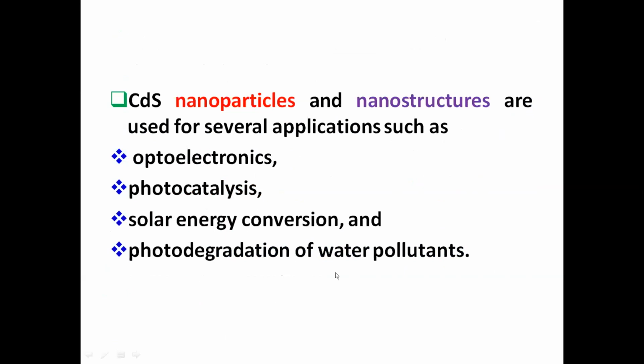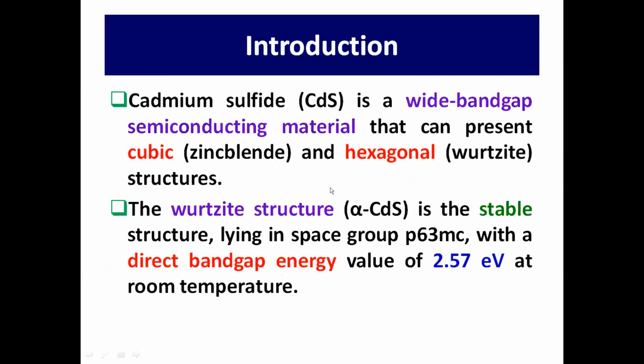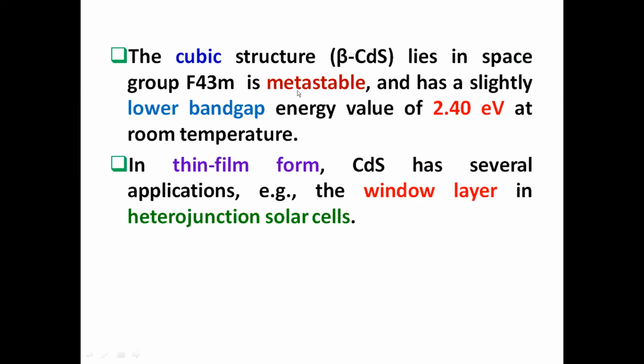Cadmium sulfide nanoparticles and nanostructures are used for several applications such as optoelectronics, photocatalysis, solar energy conversion, and photodegradation of water pollutants. The introduction. Cadmium sulfide is a wide band gap semiconducting material. It represents two phases, cubic zinc blende and hexagonal wurtzite structures. But the wurtzite structure is the stable one. It has a direct band gap of value 2.57 electron volt at room temperature. The cubic one is metastable and it has a lower band gap energy of 2.4 electron volt at room temperature.